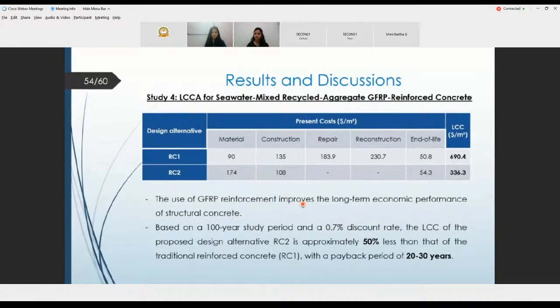The use of GFRP reinforcement improves the long-term economic performance of structural concrete, as per this table. Based on a 100-year study period and a 0.7% discount rate, the life cycle cost of the proposed design alternative, RC2, is approximately 50% less than that of the traditional reinforced concrete alternative, RC1, with a payback period of 20 to 30 years, which is very interesting.